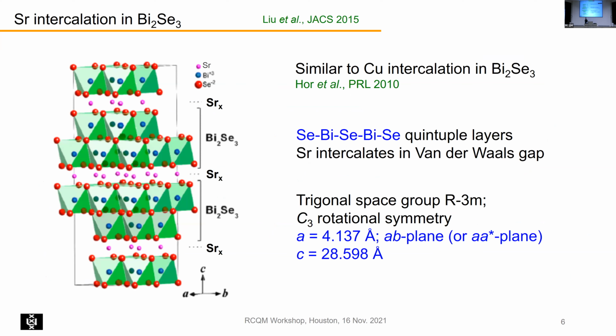The idea is that the strontium, indicated here by these pink atoms, intercalates into the van der Waals gaps. This picture is actually taken from a paper by the group of Cava, where they made a similar picture for copper intercalation. Important, the space group is R-3m, so this is a trigonal material, and we have a C3 rotational symmetry.